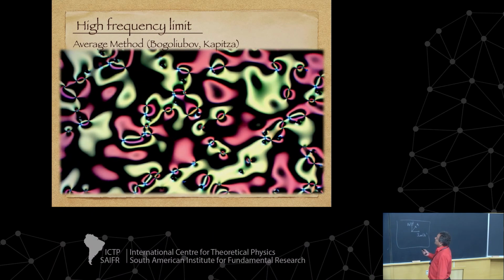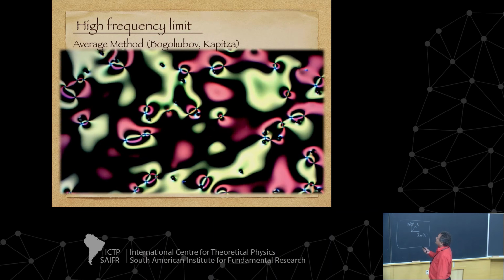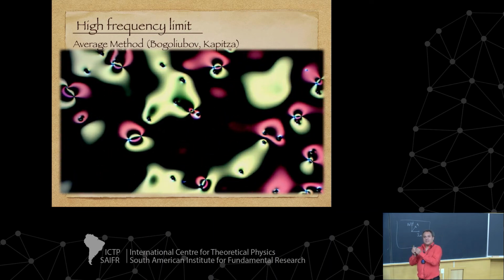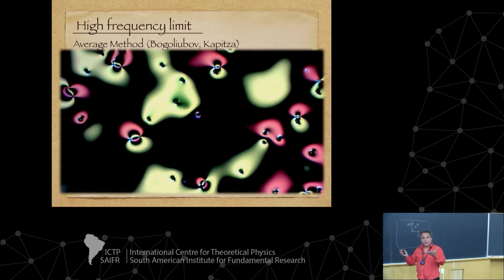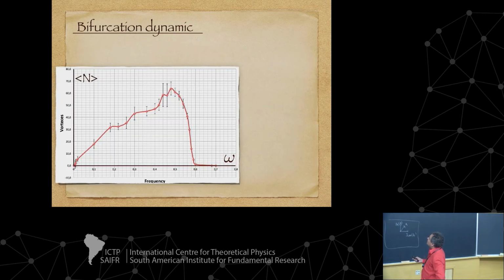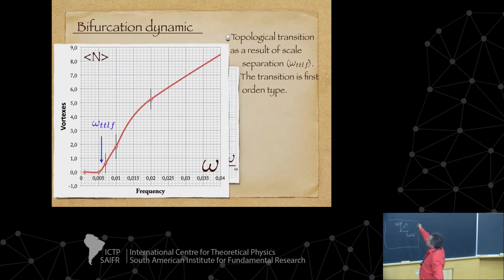So you take the system, and essentially we observe that at the typical frequency at which liquid crystal is used, a frequency in the kilohertz, for instance, we have two vortices, and they appear, and they try to annihilate. Okay, this is the frequency at which your smartphone works, kilohertz frequency. No vortex is possible. So if some vortex appears from any fluctuation, it appears by pair to conserve the topological charge, and after that they annihilate. Okay? So in this high frequency limit it is possible to explain why we don't have vortices.